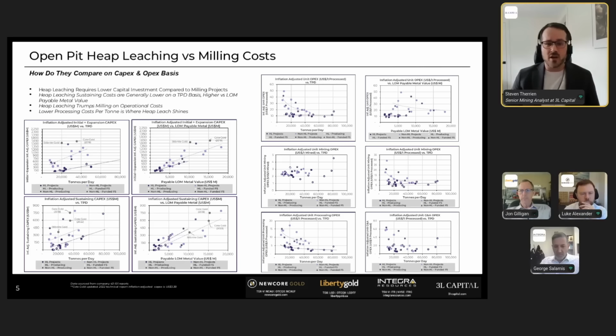On unit operating costs, that's where heap leach really shines. So across scales, doesn't matter if it's 20,000 tons per day or 80,000 tons per day, you can see that the operating costs stay low, somewhere generally between $10 to $15 per ton processed, and that's a stark contrast to milling.